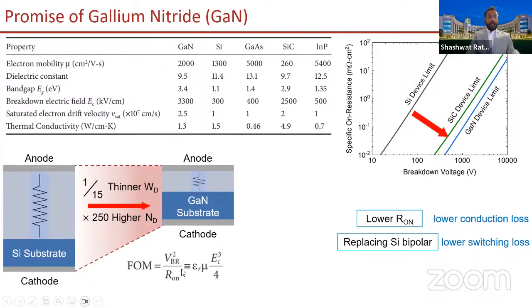And in its off state, when you don't want to charge your phone, you want the charger to block a certain amount of voltage. So it's called the off state. In the off state, the breakdown voltage becomes important, and in the on state, your on resistance becomes important. So all of this translates to a linear dependence of this figure of merit on the mobility and a cube dependence on the critical electric field.